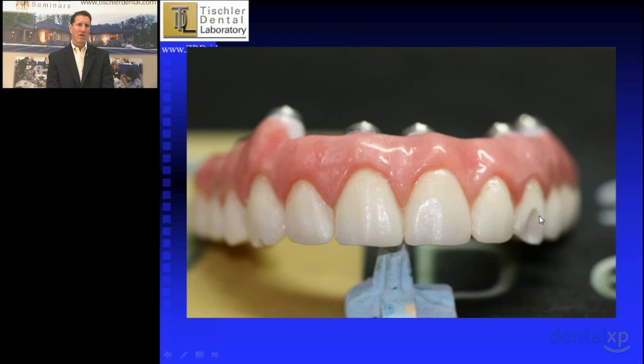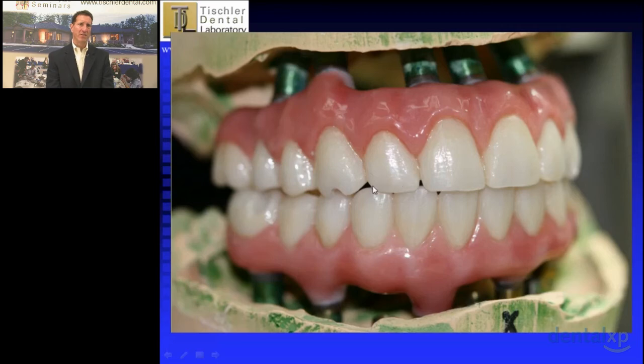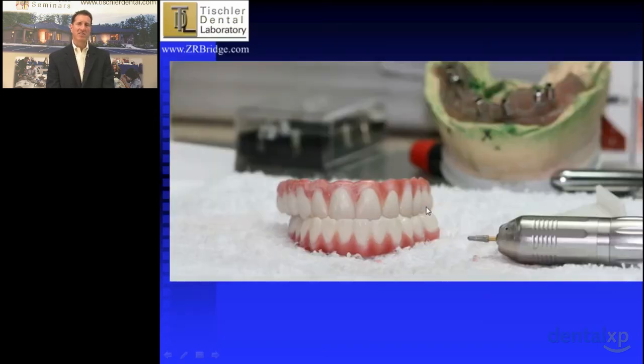But you can see that we've obtained ideal aesthetics here, and here's an example of a screw hole that kind of came out the facial, but what's nice about the zirconia is that if you put composite here, that's gonna blend in and be almost undetectable. Same thing here, a little spot there that could be filled in with composite. So this is full contour zirconia here. This is a B1 shade, I believe. And you can see that we have ideal aesthetics. This will not chip, this will not stain, and this will be there for many, many years to come.